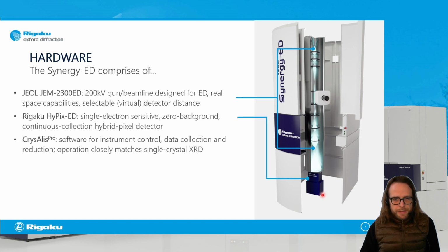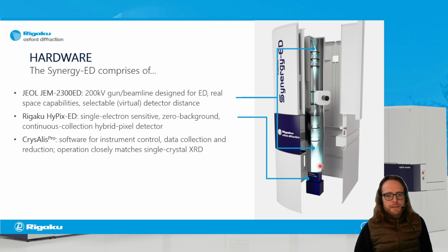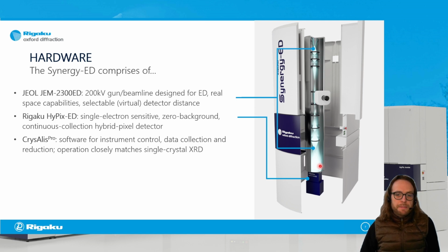Next, we have the detector here. It's the Rigaku HyPix-ED. This one is based on the Rigaku's proprietary HyPix hybrid pixel technology. It is pretty much the same detector as is on all our other Synergy instruments, just adapted for use inside the vacuum of an electron diffractometer. And as importantly, we have CrysAlisPro running, which controls this detector and also the entire electron column, and also does the data reduction in real time and couples directly to further data analysis like structure solution and refinement, as you would expect from a state-of-the-art diffractometer. And again, you will see that later on in the demo.